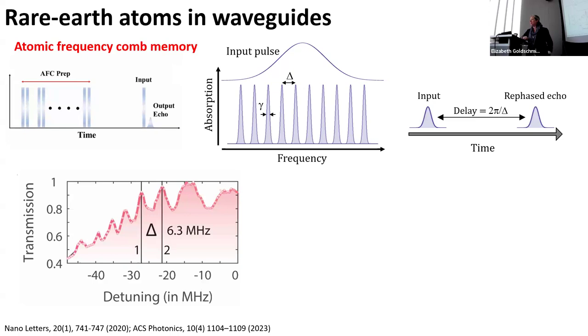Our optical lifetime was not a lot faster than our long-lived state. You're shelving atoms to make the comb, but it's like filling a bucket with a hole in it. If the rate at which you're filling the bucket is too slow, which is like your optical pumping rate being too slow, and the bucket is too big, which is like the lifetime of your metastable state being too short, you're not going to do a very good job of filling the bucket.